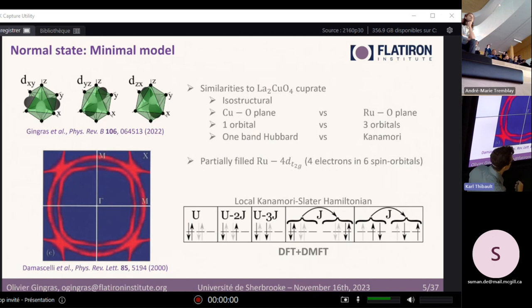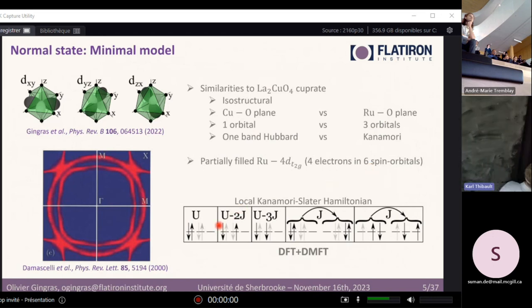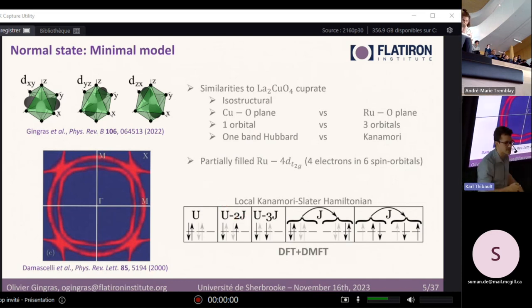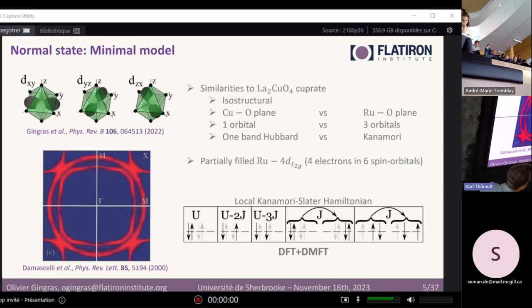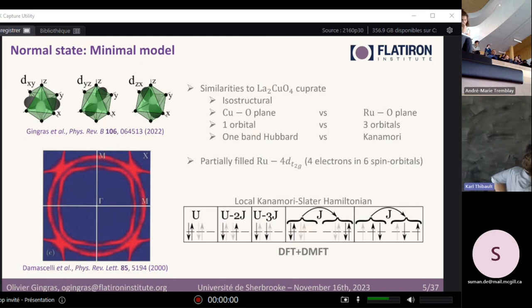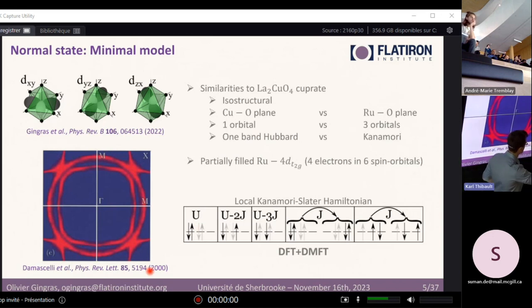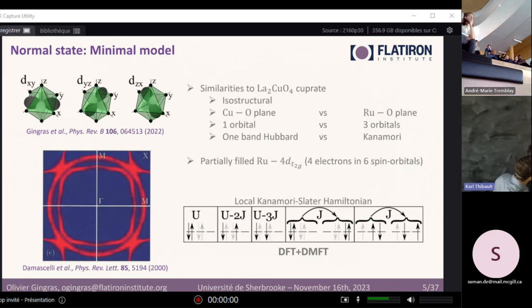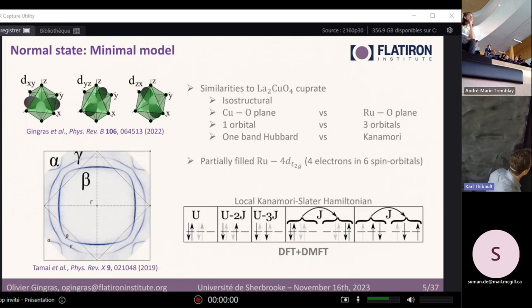Typically, we use the Kanamori interaction, which is essentially the same thing as Hubbard, but for multiband. So you have an on-site Coulomb repulsion cost U. But if you're on different orbitals and with the spin being aligned, it's less energetically costly to be in such a configuration due to Hund's coupling, which favors same spin alignment. And this is the interaction that would describe this material. If you do DFT with this to study this material, and then you include the lacking local correlation with DFT plus DMFT, then as we will see, there's a beautiful agreement with experiment, in particular here, the Fermi surface, the old one and the new one. There's a beautiful agreement.